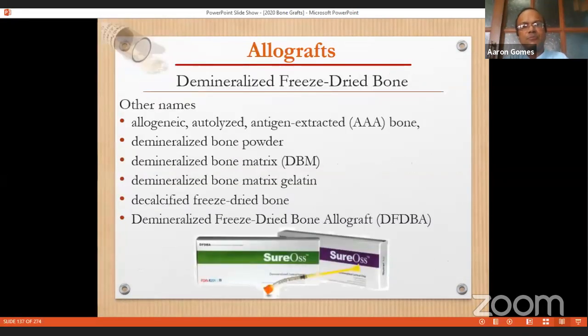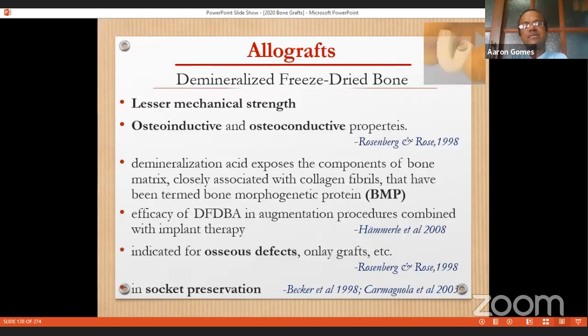The demineralized freeze-dried bone allograft is also called allogenic autolyzed antigen extracted bone or demineralized bone matrix, or during my residency days we used to call it DEM bone, and we liked it because of its easy maneuverability into the defect site whenever you mixed it with a little bit of blood. However, it has lesser mechanical strength as compared to the freeze-dried bone allograft, but it has osteoinductive potential simply because the demineralization process exposes the bone morphogenetic proteins, while in the case of the freeze-dried bone allograft, these proteins got sequestered by the calcium which was not demineralized.